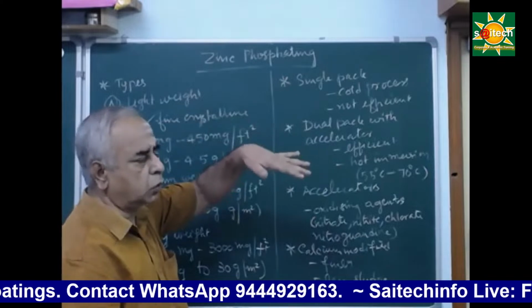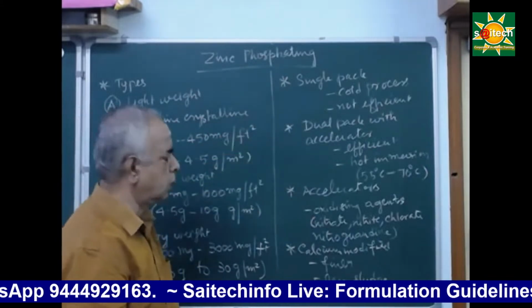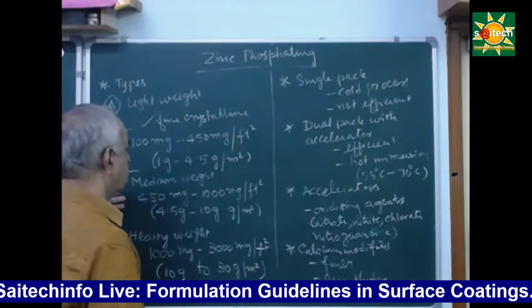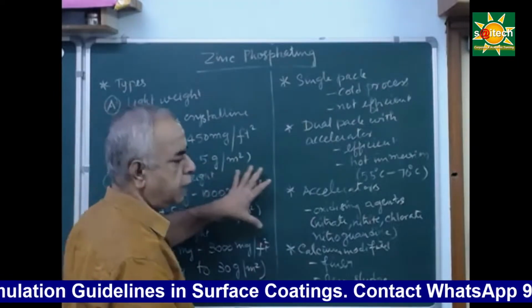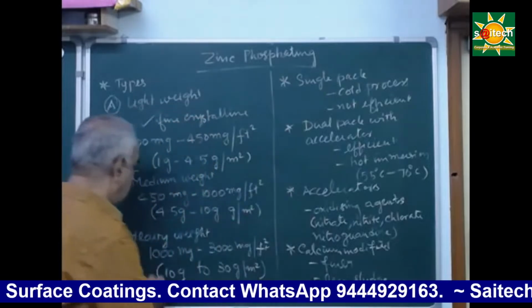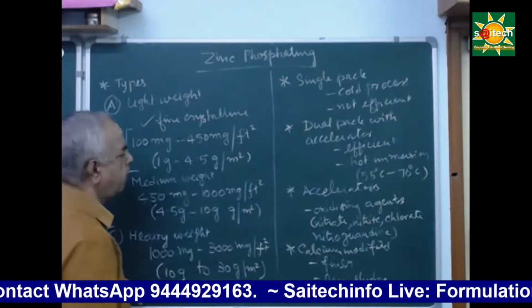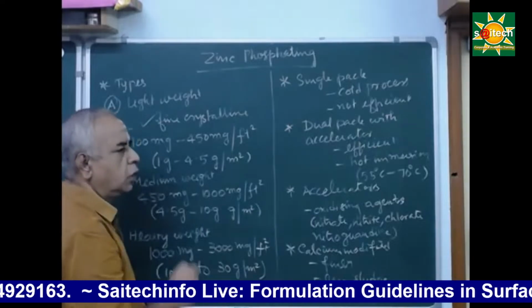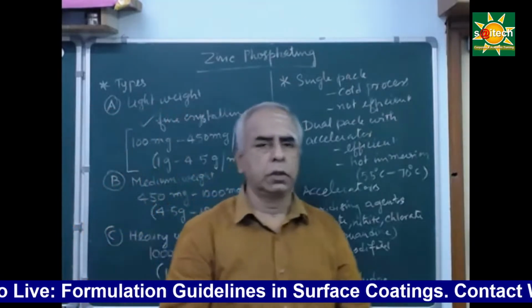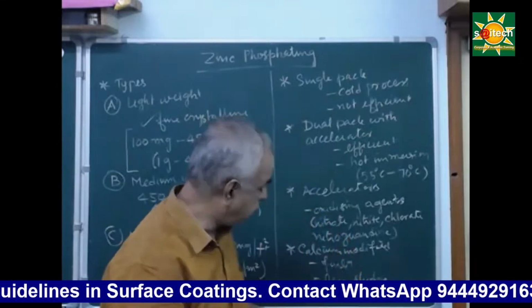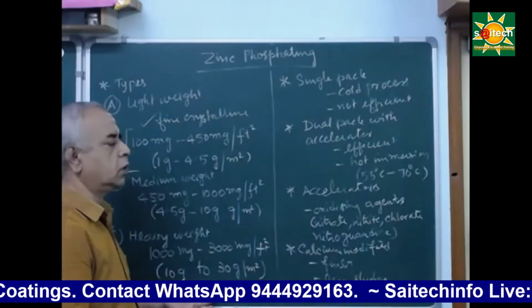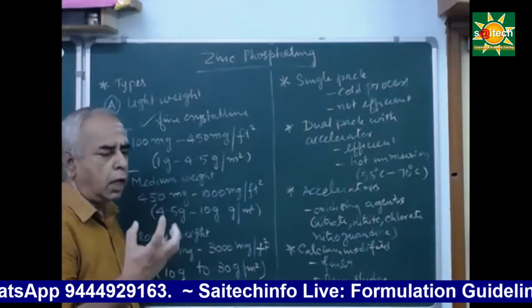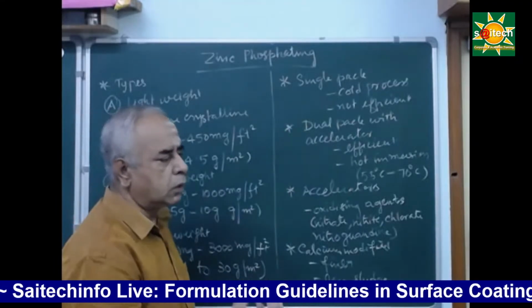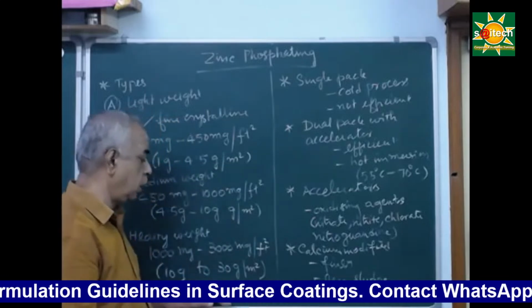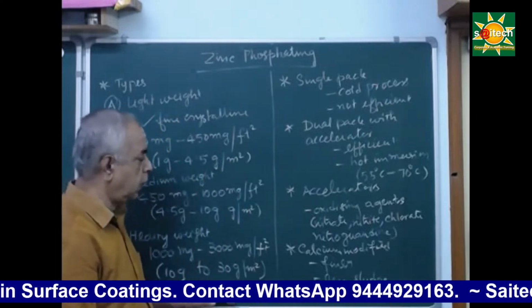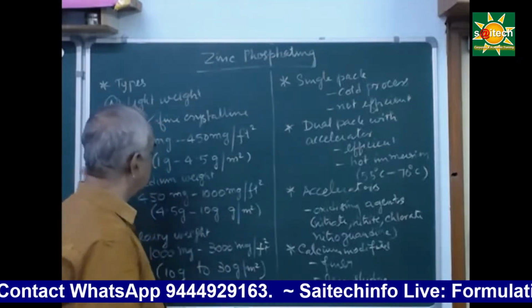There will be moderate corrosion resistance in terms of salt spray resistance hours. But when you go for medium weight, this is always ideal for any automotive industries. And this is somewhat of a heavy weight nature. So with the increase of coating weight, you can have better corrosion resistance, but it will sometimes complicate also. The heavier the coating, the more hygroscopic tendency it will have, so that the water test may be a failure. So take care. I would always suggest to go for the medium weight.